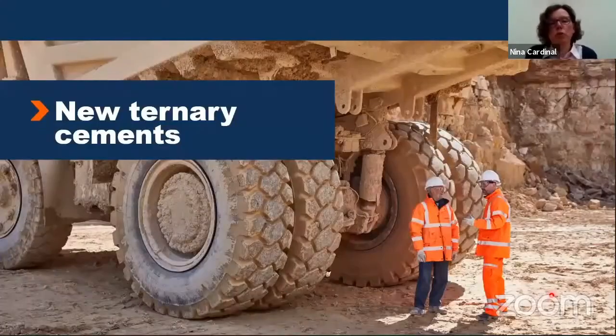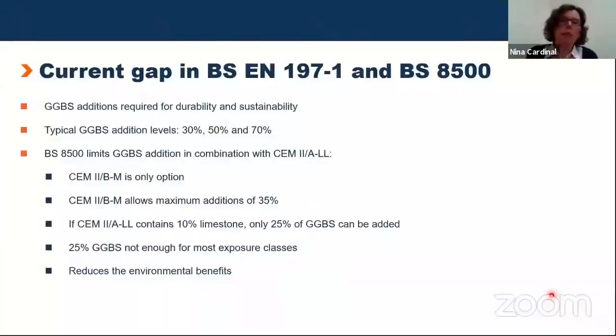I will now introduce the new so-called ternary cements. Ternary, the word says already, basically 3 components to the cement. What is the gap in the current standard for cement, EN 197-1, and the British standard for ready-mix concrete, BS 8500? I have explained that GGBS additions are required for durability, and we also want them these days for sustainability reasons. Typical additions of GGBS in the UK can already range from 30 through 50 to 70%.